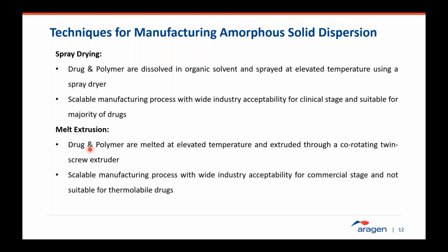And the second most widely employed process is melt extrusion, where the drug and polymer are melted at an elevated temperature, which is determined during the process development. Appropriate temperature where drug and polymer are miscible and also not degrading. At that particular temperature, the drug polymer mixture is extruded through a twin screw extruder and made into granules, which are further processed to make into capsules and tablets.